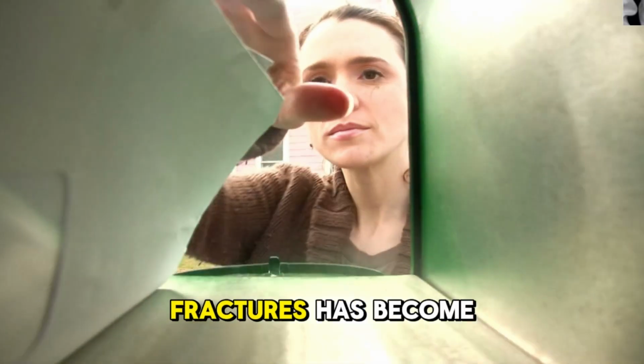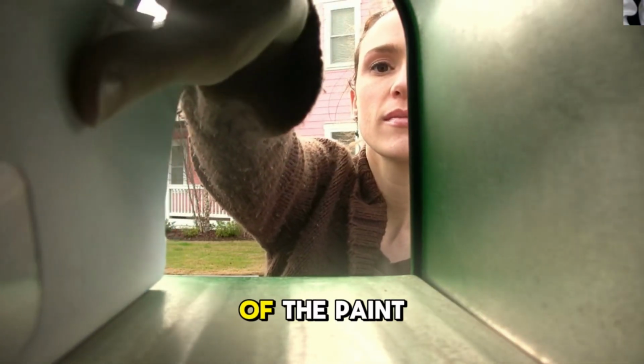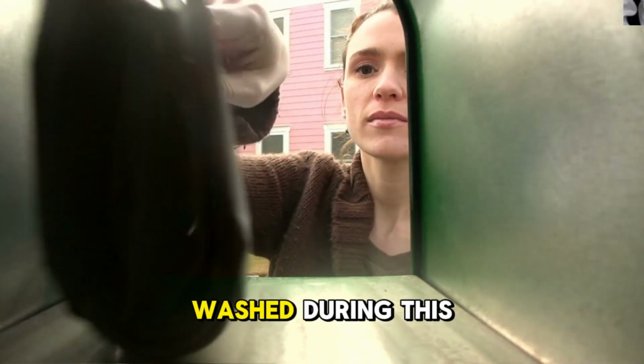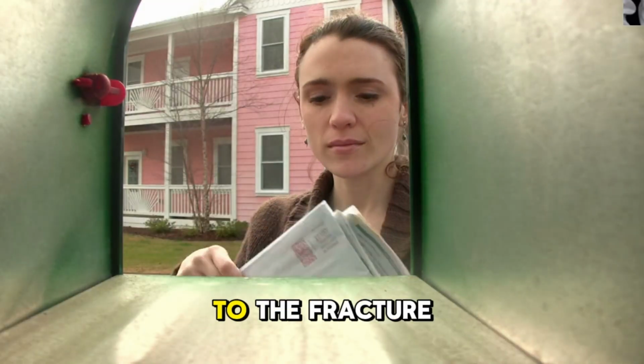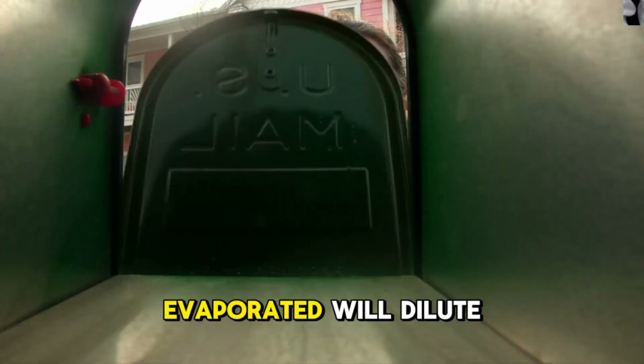By the end of 48 hours, at typical ambient temperatures, the cross-linking reaction is substantially complete, and the resin network inside the fractures has become a permanent structural feature of the paint film. The vehicle should not be washed during this period, as water introduced to the fracture network before the carrier has fully evaporated will dilute the resin concentration and reduce cross-linking density. After 48 hours, normal washing and use can resume without any effect on the treatment.